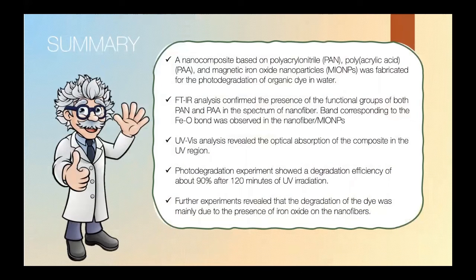In summary, a nanocomposite based on polyacrylonitrile, polyacrylic acid, and magnetic iron oxide nanoparticles was fabricated for the photodegradation of organic dye in water. Photodegradation experiments showed a degradation efficiency of about 90%. Further experiments revealed that the degradation of the organic pollutant was mainly due to the presence of iron oxide on the nanofibers. We further recommend the thorough investigation of other parameters to improve the performance of the proposed composite material.